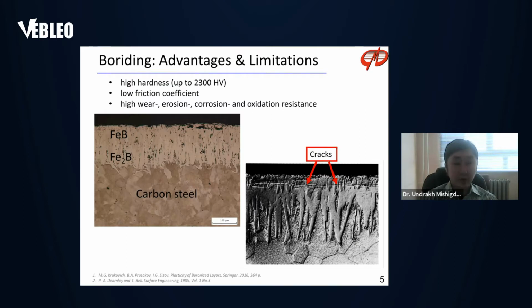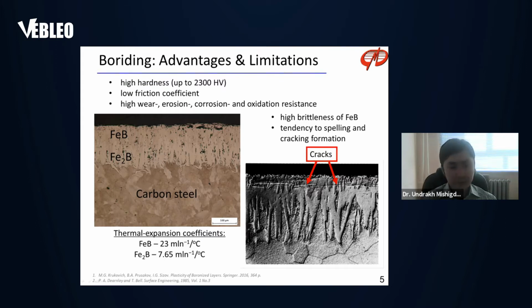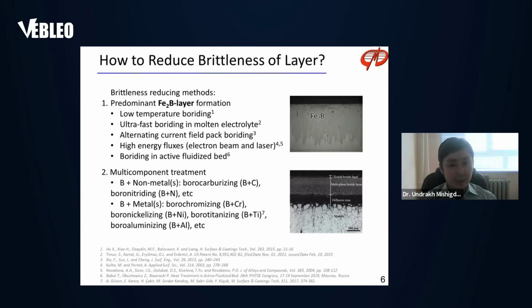Despite a number of advantages, boriding has limited application because of the high brittleness of the FeB phase and its tendency to spalling and crack formation. This is due to the thermal expansion anisotropy of iron borides. Besides, it is known that Fe2B produces compressive residual stresses while FeB produces tensile ones. So there are several methods of reducing the brittleness of the boride layer.